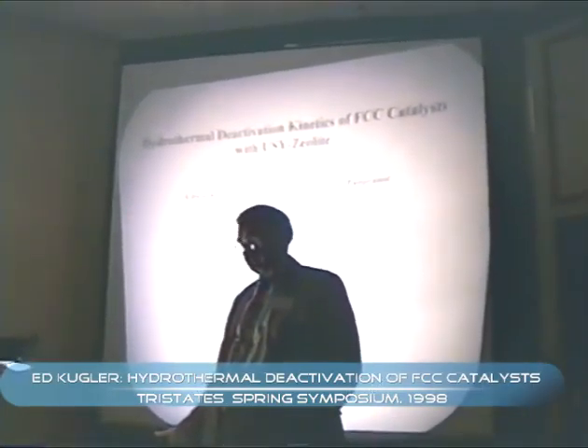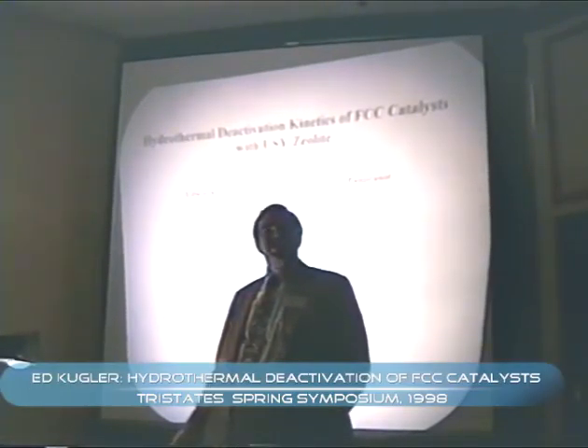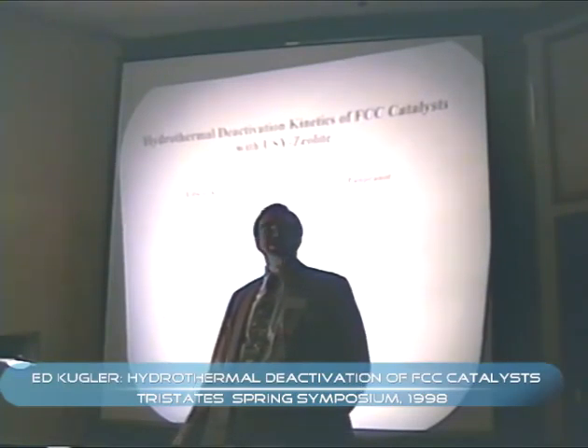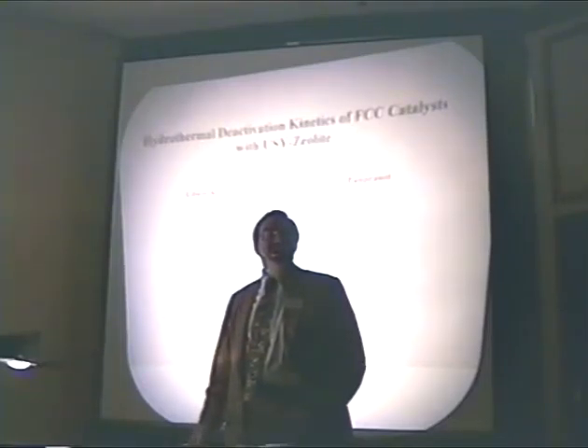In evaluating an FCC Catalyst, what we typically do is hydrothermally deactivate it first. One reason is that it mimics the environment that the catalyst sees in a commercial FCC unit. The steaming also brings about physical and catalytic changes. Cracking real feeds on an unsteamed catalyst typically makes a lot of coke — around 10% with fresh catalyst. If you steam for as little as an hour, coke make drops to about 2%, and you also see an increase in gasoline yield. These are very favorable from a refining standpoint, probably related to the loss of very high active sites giving hydrogen transfer reactions and coke-making reactions.